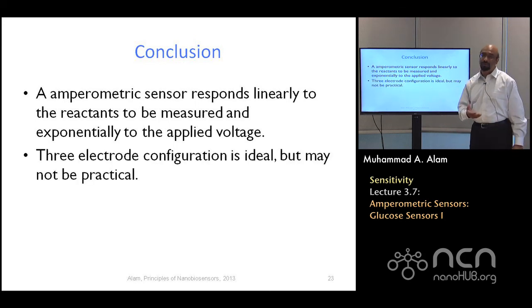Now, I mentioned the 3 electrode configuration is very important in order to get specific reference voltages for each one of the electrodes. Because otherwise, the partitioning of the voltage between the working electrode and the reference electrode may not be well defined. And if it is not well defined, then it will not be a very robust or predictable sensor. But in many cases, putting in 3 electrodes is difficult. And so in that case, working with 2 electrodes requires extensive calibration before you should take the results for granted.